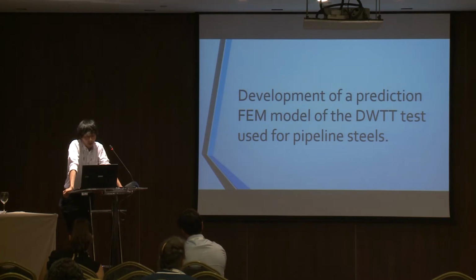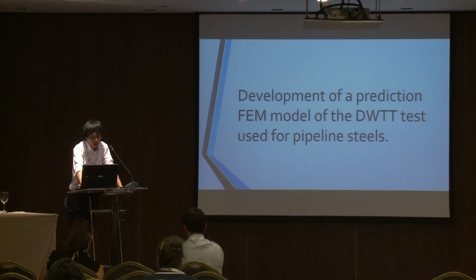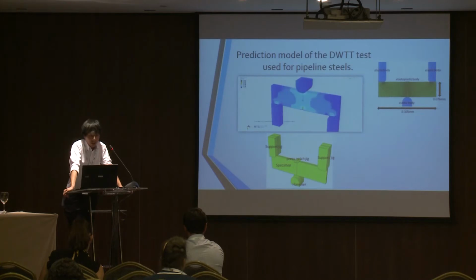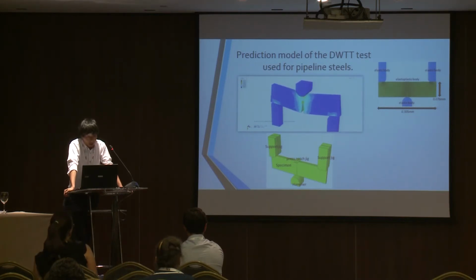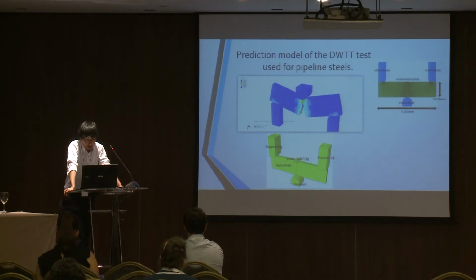Next, I'll talk about developing a prediction FEM model of the DWTT test used for pipeline steels. Please show the movie of the prediction model of the DWTT test. The fulcrum supports are located on both sides. The hammer is an elastic body. The test piece is an elastoplastic body, and the upper part of the test piece is press-notched. The initial speed of the hammer is 7 m per second.